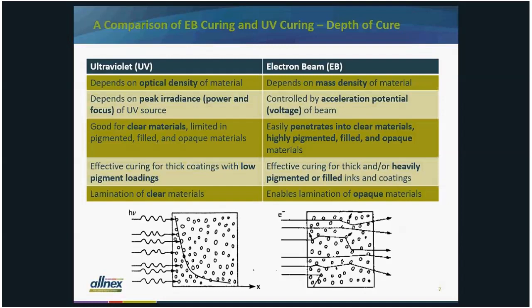One of the key aspects of energy curing is how to cure down through the entire thickness of the coating or ink. This isn't such a big problem with heat-cured substrates because eventually, when you put something in an oven, everything will get hot. But depending on the materials in your formulation, everything may or may not see sufficient energy to cure. So if we look at the differences between ultraviolet and electron beam curing from the depth of cure perspective, the depth of cure in UV curing depends on the optical density of the material, whereas in electron beam it depends more on the mass density of material.